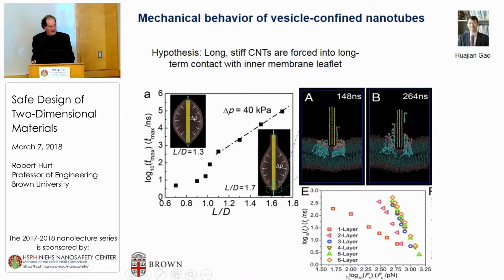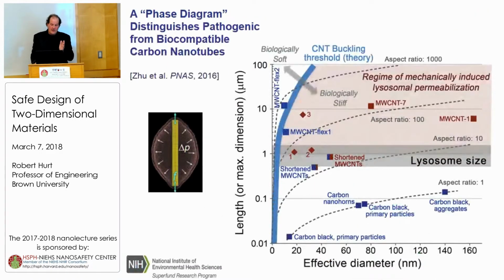So he's developed a theory that as nanotubes get longer, they're forced to press against the inner leaflet of the lysosome membrane. And as they press, if they're hydrophobic, they begin to extract lipids. And you can get a cascade of lipid extraction from the inner leaflet of that membrane that causes the damage. And so that's our current molecular level theory of how that damage takes place. But it certainly, we know, is triggered by nanotubes that reach a certain critical length.